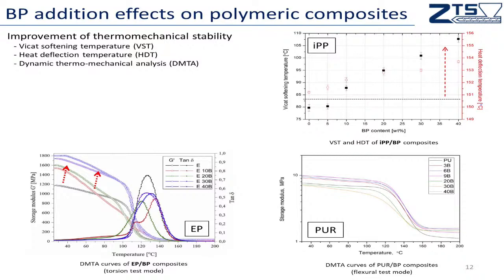However, some of the changes of the properties were comparable for all of the materials. So the first approach that was the most important for us was the improvement of thermomechanical stability, extending the field of application of the material by increasing the temperature of its use. So we improve the stiffness at elevated temperature. We measure it in static and dynamic conditions.